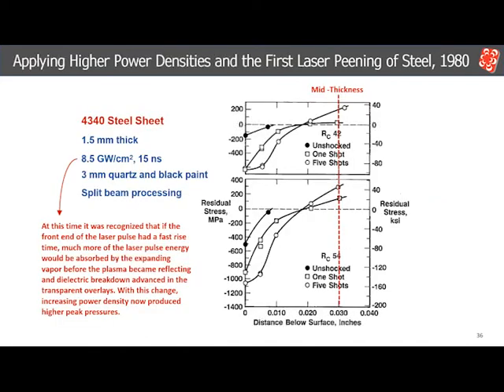We began looking at laser peening steel in 1980. First investigated was the hardness dependence of the residual compressive stress. In 1.5 millimeter thick steel sheet, the residual compressive stress produced in the hardest condition, Rockwell C54, was much higher than that produced in the softer condition, Rockwell C42.